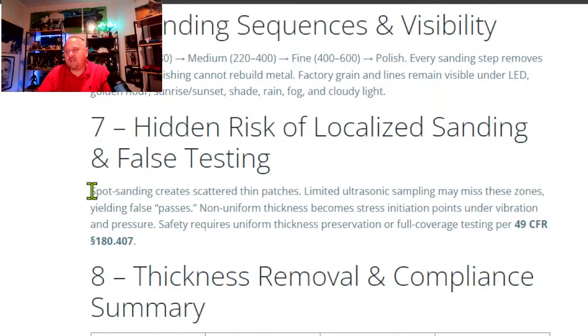When something is thickness tested, it's tested with the ultrasonic testing machine that everyone in the industry is aware of, and it's done in one spot. It may be done in 3 different panels, 4 different panels around the unit, but the unit is not tested over the entire surface. Typically it's not, and we're talking about every square inch of the entire surface of a tank. Typically that's not done.